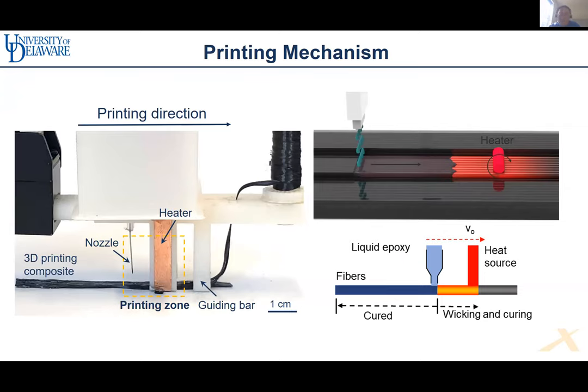Here we invent this heater. By using carbon nanotubes, because carbon nanotube structures are highly conductive, if we apply electricity, we can quickly control the heating rate. And here you can also see the nozzle. The nozzle will adapt the gradients onto the fibers, and the heat can transfer along the fibers toward the other end. So in this case, we can create a gradient temperature distribution along the fibers.